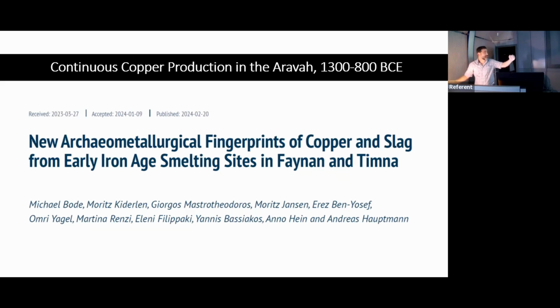It's very important. The group of Bode and Kiderlen, for example, quite a few years ago, were able to show that in this particular period, 10th century, 9th century BCE, the copper of the Araba went all the way to Greece. They analyzed copper from Delphi and Olympia and were able to show by the chemistry of the tools that the copper in the Araba was not only for local consumption. It went far away. And since then, there were other studies showing a similar trend. So for a certain time in the history of actually the Eastern Mediterranean, the Araba was the major supplier.